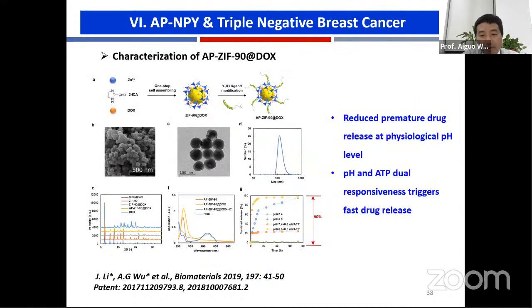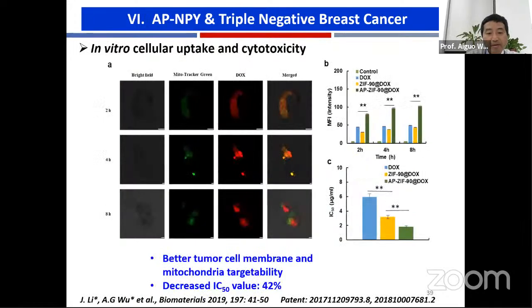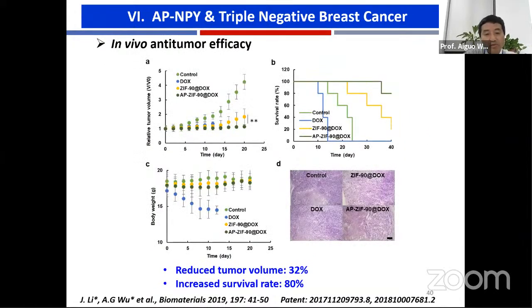And we found it reduced the premature drug release at the physiological pH level. And also there is a kind of pH and ATP dual responsiveness that triggers the fast drug release. And we found also better tumor cell membrane and mitochondrial targetability, decreasing the IC50 value by about 40%. So up to now, we don't know why there is a kind of cell membrane and particularly mitochondrial targetability. For that reason, we are also researching. And we found this nanosystem can reduce the tumor volume by over 30% and also increase the survival rate by about 80%.